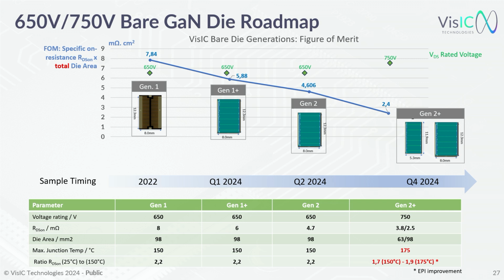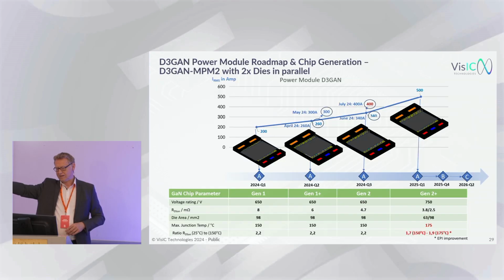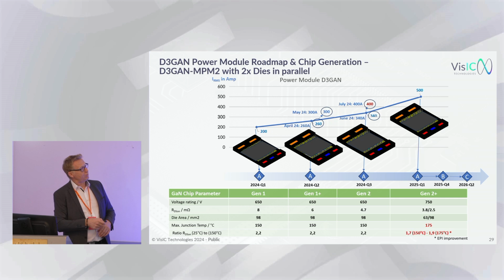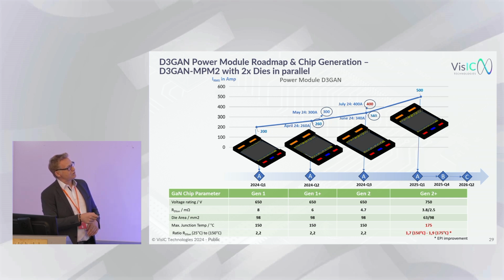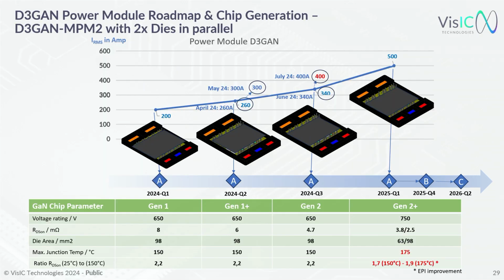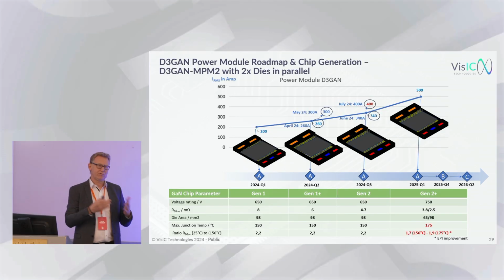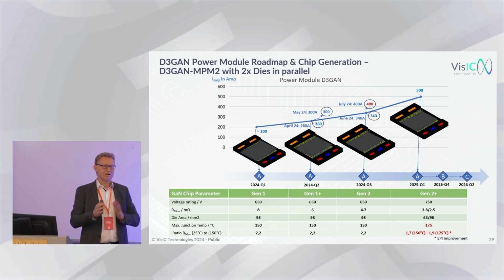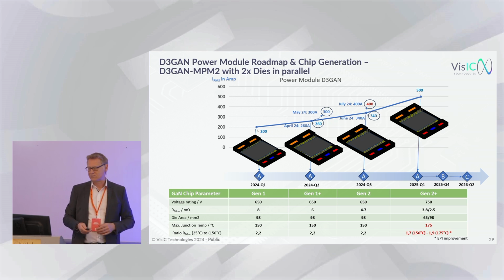So just as a device roadmap, where we are now is here. This one I showed. This is the next one, which was just coming out of fab with 4.7 milliohm. And we are now working with a 2.5 milliohm in the same chip size, which is coming before the end of the year. This will enable us, in the same power module form factor which we have now at 300 amps, to go to 400 amps, and then even above 500 amps in the same form factor, so that we can basically replace silicon carbide directly with gallium nitride in the same form factor.